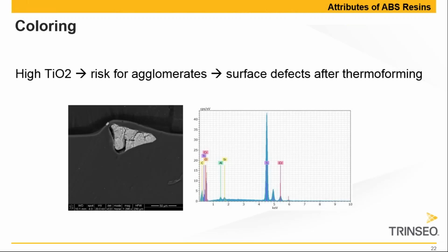There is another risk in using high amounts of master batch, and that is risks for surface defects. The picture on the left side is an electron microscopy picture of a cross-section of a sheet right through a surface defect. You see this wave at the upper side of the picture. That is in fact the surface of the sheet. And the surface showed a local deformation due to an inclusion.